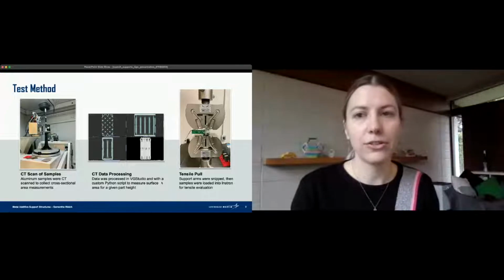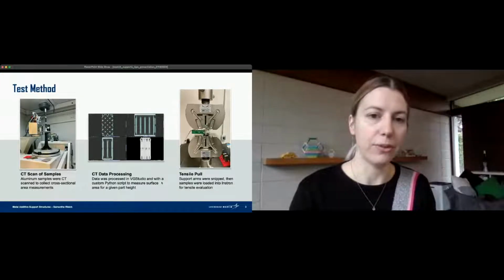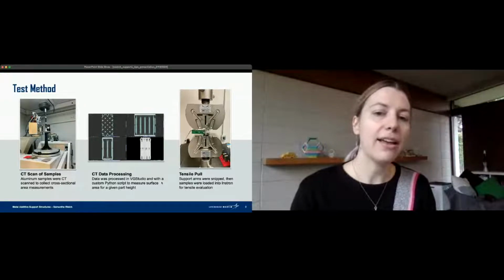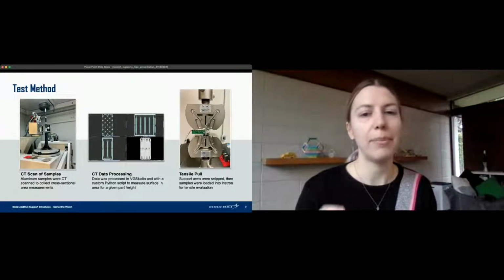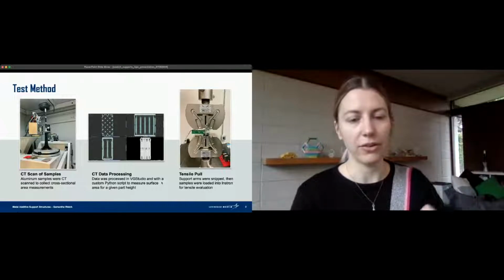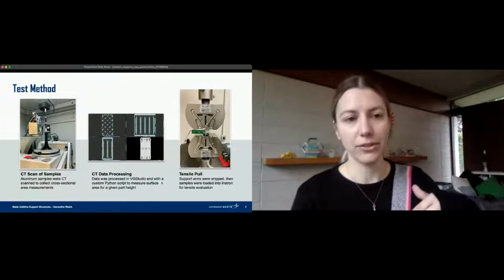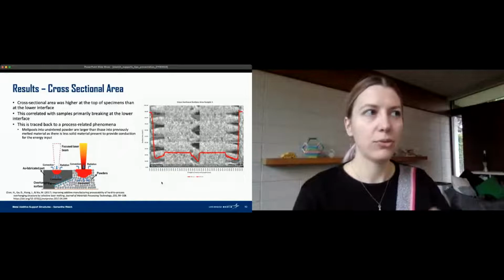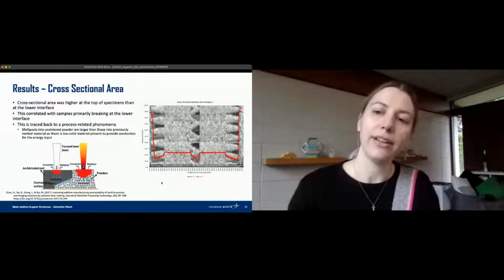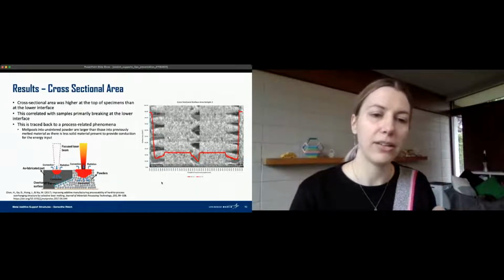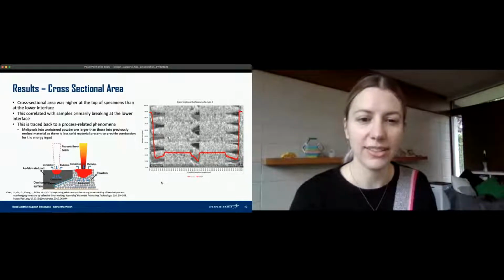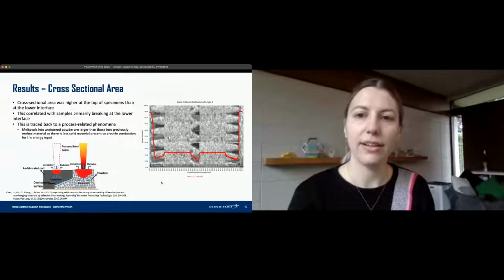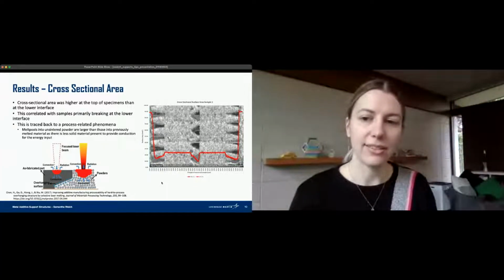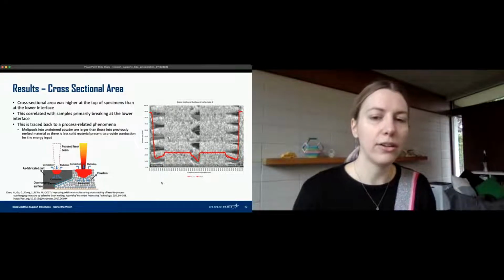So some of the first results that I found quite interesting were from this cross-sectional area. I had assumed that the top interface would be my weaker interface, where the support ends and my part builds. I thought that would be where things were likely to break, but that wasn't what I was seeing. I was seeing my tensile bars were frequently breaking at that lower interface, and this was also reflected in the CT data as well. It was a small difference, but consistently they were slightly larger in cross-sectional area at the upper interface than the lower interface.